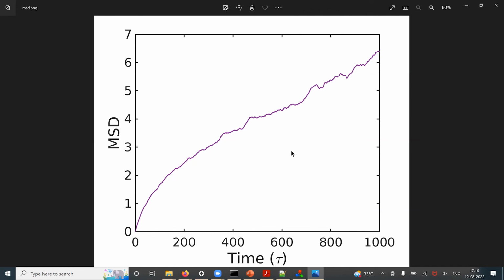It depends on the property you want to measure. So let's say mean square displacement you want to measure. You have multiple sizes from 2000 all the way up to 200,000, right? In steps of some number. So let's say 2000, 10,000, 50,000, 200,000. These are 4 data points you have, right? You see that the data is not changing from 10,000 to 50,000. Then you know that, okay, maybe slightly more than 10,000 is good enough. And then you can do a finer resolution there. From 10,000 to 50,000, you can have steps of 5,000 and see what size is good enough. Okay. This is something you have to do initially. This is like benchmarking your system.